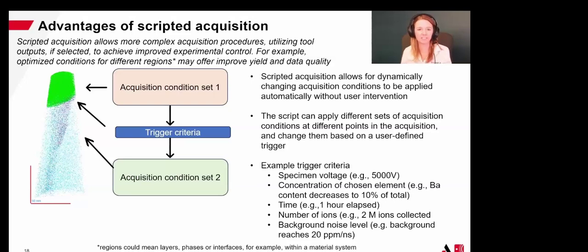Now, in the case of our off-the-shelf MLCCs, one of the things that we're interested in is the interface between those nickel electrodes and our barium titanate matrix. Because again, interesting things happen at interfaces. Now, as you might imagine, a metal and a ceramic might have different field evaporation behavior and different preferred conditions in the atom probe acquisition. So one of the things that we can do is choose different acquisition conditions to be applied automatically at different stages of our acquisition. So for example, as we're evaporating through our nickel electrode, we can choose a set of acquisition conditions to be applied.